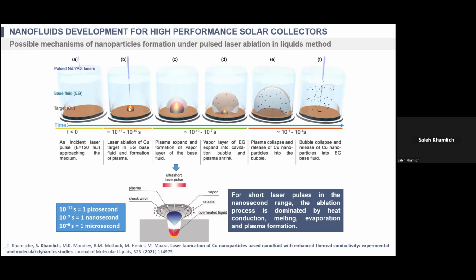Highly energetic. This plasma will grow with time, and this process happens at the picosecond regime, very fast. Because the plasma is very hot, the surrounding liquid around the plasma will be evaporated, which means you will have a vapor of the molecules of the liquid, which is ethylene glycol in this case. There is a lot of physics around here, thermodynamics and so on. After some time, at the nanosecond regime, the plasma starts to shrink in a fast way, and this cavitation bubble starts to grow. It grows, it grows, it grows.